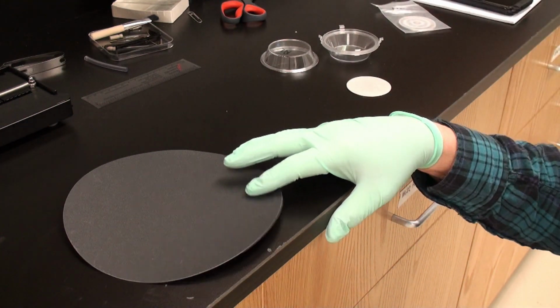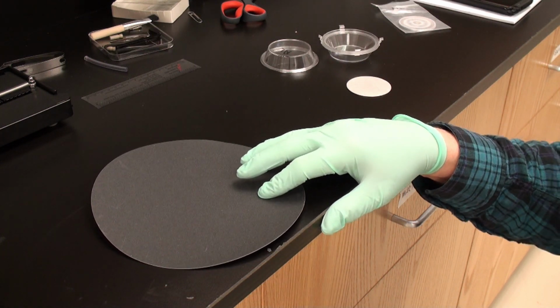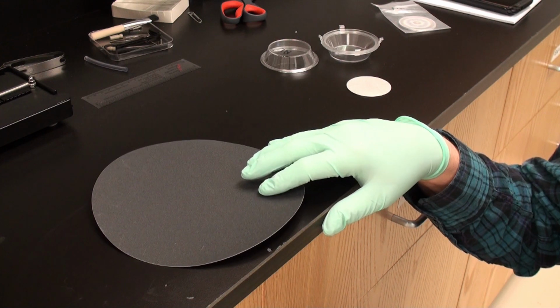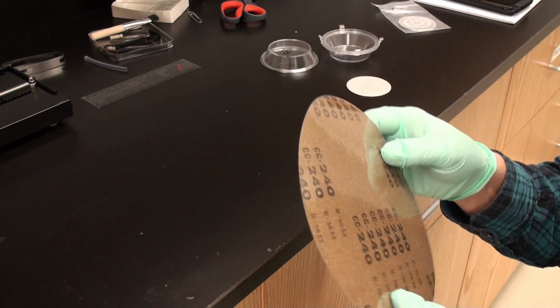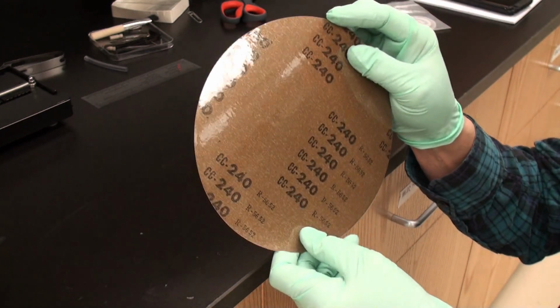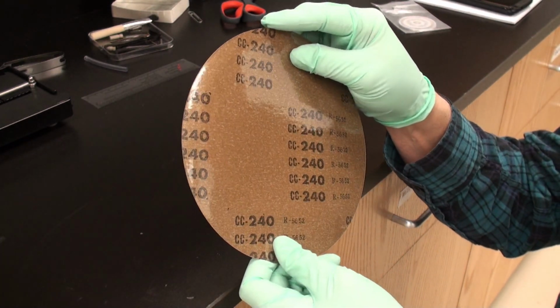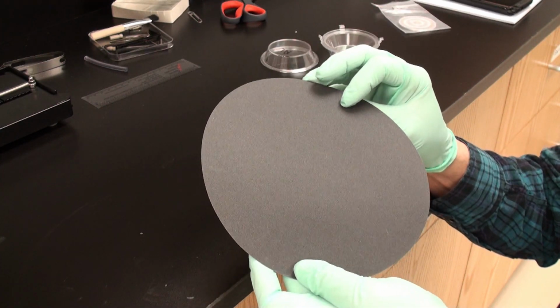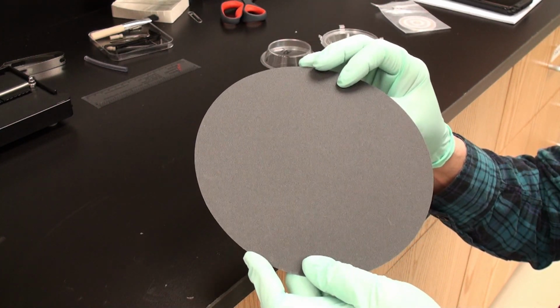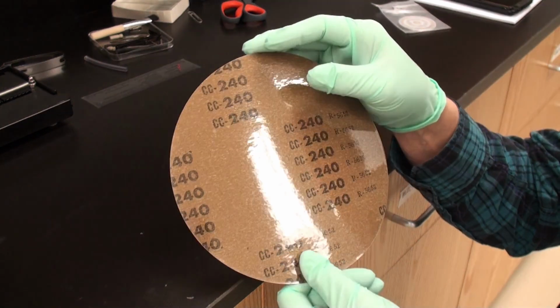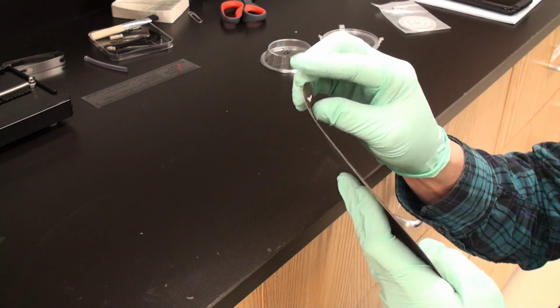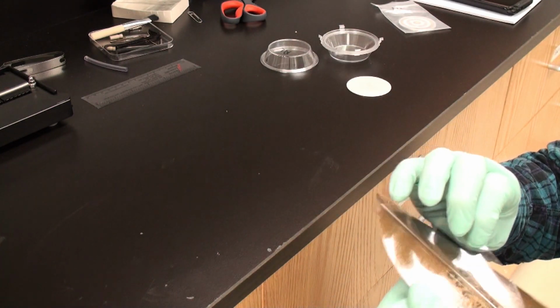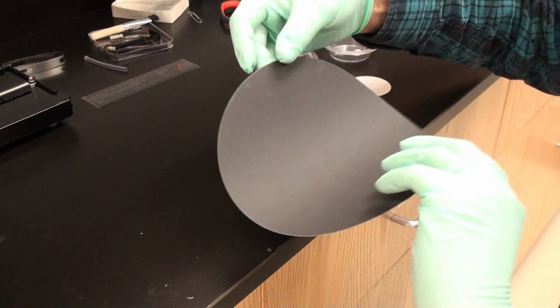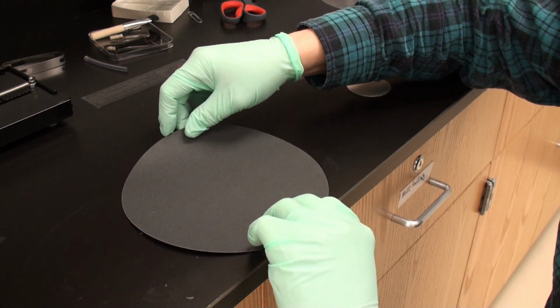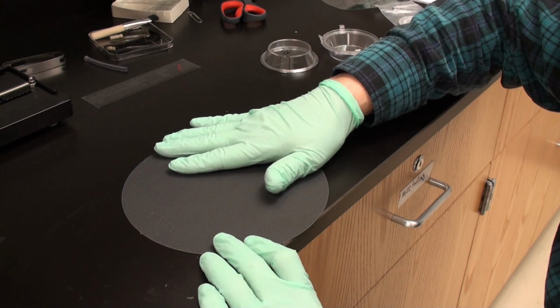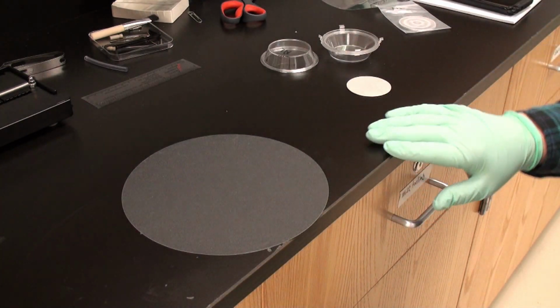You need to abrade the surface and remove as much oxide as possible before installing them in the unit. My usual mode of operation is I use standard materials preparation grinding discs. This is 240 grit with a stick-on backing. This way the material will stay put on the bench top and I can easily peel it off.